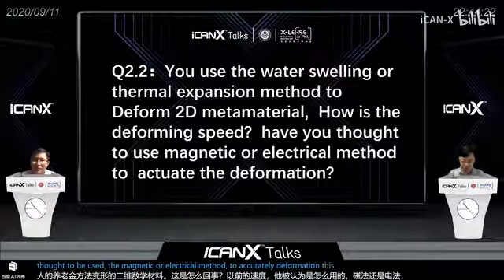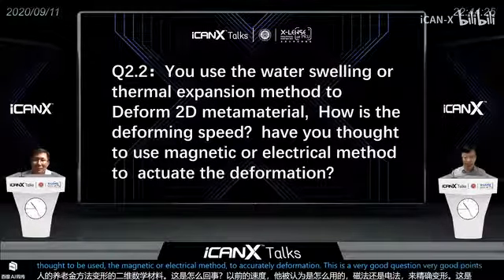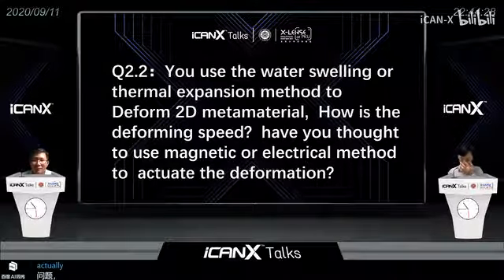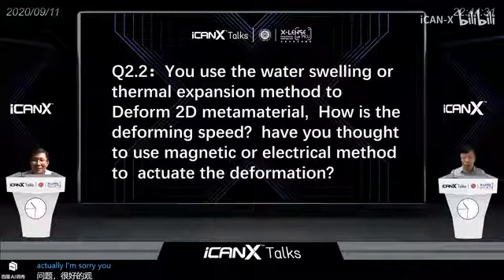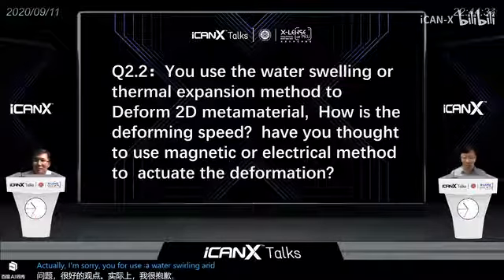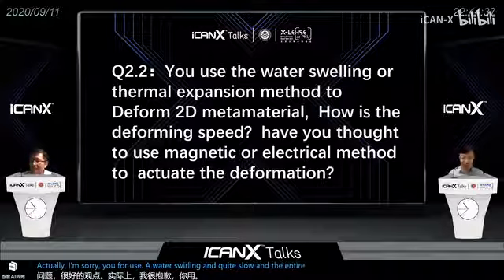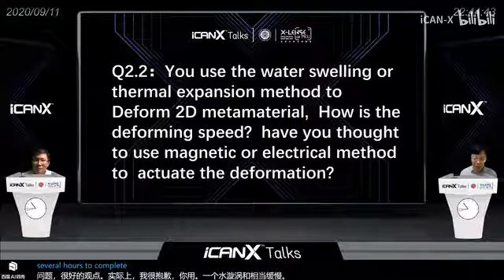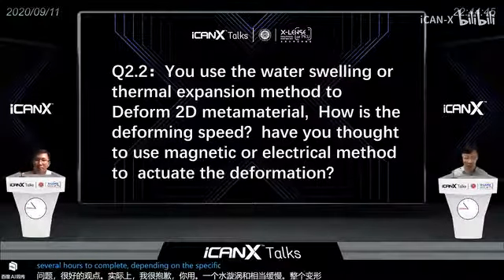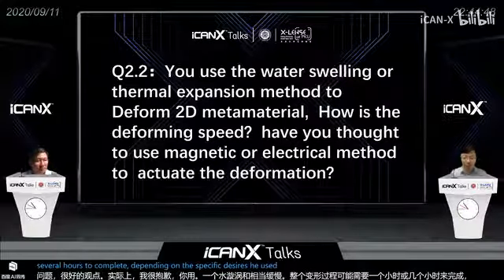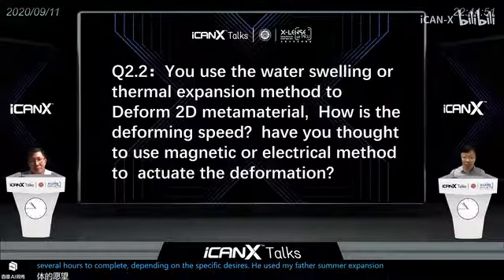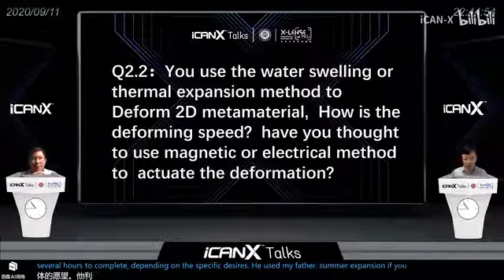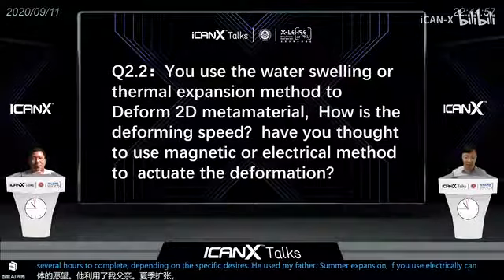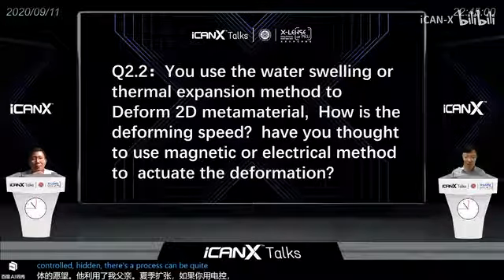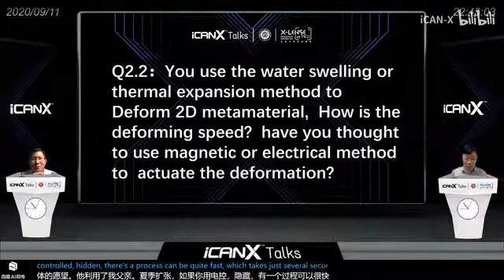Yeah, this is a very good question. Very good points. If we use water swelling, then it's quite slow, and the entire deformation process can take around 1 hour or several hours to complete, depending on the specific designs you use. But for the thermal expansion, if you use electrically controlled heating, then the process can be quite fast, which takes just several seconds to complete.